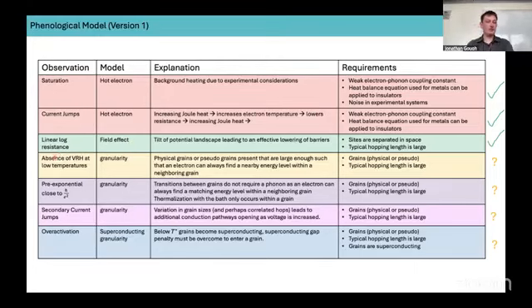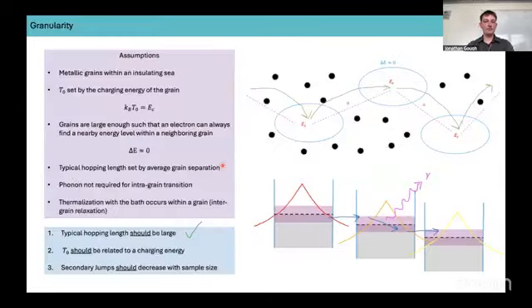So the rest of our observations, namely this absence of variable range hopping, all tie into this granularity model, which is still something that's being developed and worked on. The main assumption of this granularity model is that at low temperatures, you get these effective grains forming within your system. So instead of hopping between disordered sites, you now get hopping between these grains. These are metallic grains within an insulating sea. So rather than the gap energy being set by the disorder, like in variable range hopping, it's now set by the charging energy of these grains.